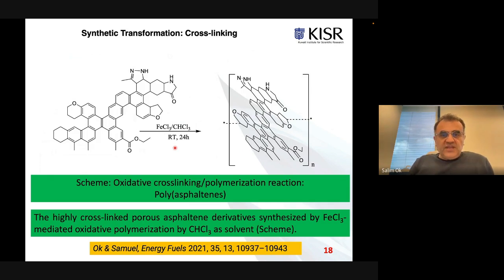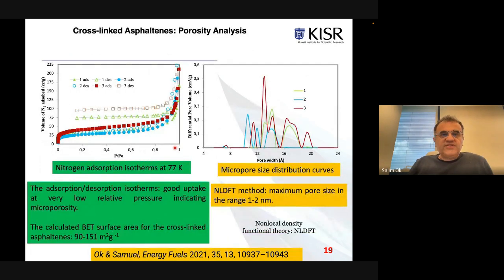Then, to characterize those samples, we conducted several different experiments. For example, we focused first on determination of the surface area of those cross-linked materials, and we recognized that the surface area is between 90 and 151 meters square per gram.